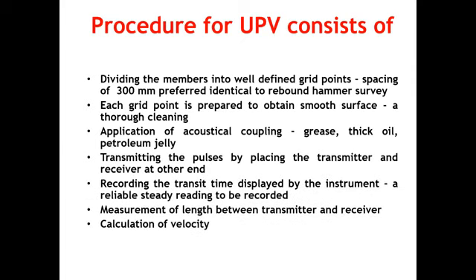But now, if the grade of concrete is more than M25 and the velocity is less than 3.5 kilometers per second, your concrete is doubtful. And for concrete up to M25, a value less than 3.25 is doubtful. So this is the quality practice we have been following in PMCs. A lot of PMC consultants are coming to India from abroad, and we started slowly tightening the specifications. One of them is this: anything less than 3.5 is not acceptable if it is M25. So we cannot apply 13311 and say that 3 is all right.